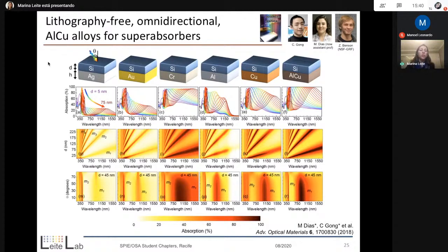And what she saw was the following. When we compare usual metals for plasmonics and photonics, such as silver, gold, chromium, which is really tricky to make high quality, aluminum, copper, and then the combination of aluminum and copper, what she saw through analytical calculations here is that the light absorption would get really high for chromium. So we're very excited about that, but we thought, okay, how can you make high quality chromium? That's very tricky, not trivial at all.